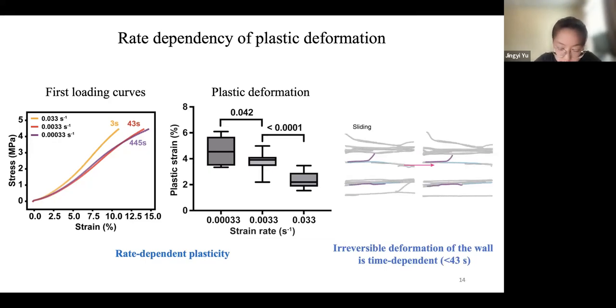And this generates some very important molecular insights, in that it is indicating that the plastic deformation is not likely coming from bond breakage in the cell wall, because one would expect that the faster we stretch the material, the more bond breakage we would introduce, thus more plastic deformation, which is not the case here. So combined with our observation in the modeling data, where we show that the sliding between cellulose microfibrils is the major contribution to the plastic deformation, these experimental results further show that sliding is more likely to be the mechanism for plastic deformation, as this is a motion that likely requires a certain amount of relaxation time, probably within the range of 3 to 43 seconds.